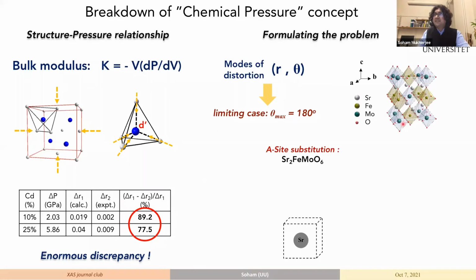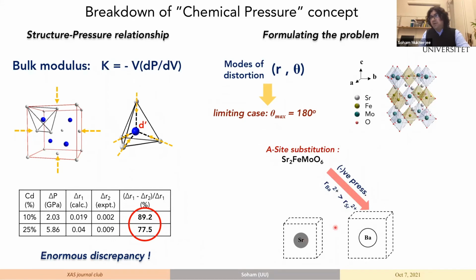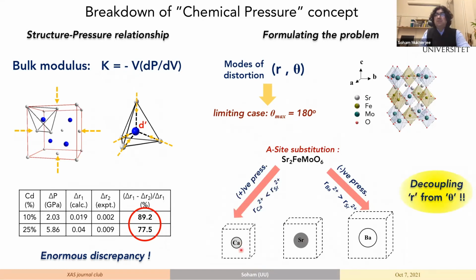And this takes us to double perovskite materials, where at the A site there is strontium, and by doping the strontium with the bigger ion barium, we explore the negative chemical pressure, and we experience positive pressure by doping in calcium. And the trick is that Sr2FeMoO6 has a tetragonal unit cell.